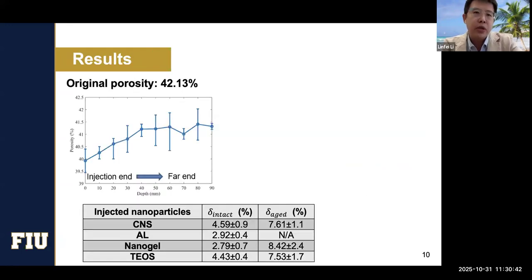So here are some of the results we have. First of all, we measured the porosity of the cement. As shown in the previous slides, the cement itself has around 40% porosity. We measured exactly the same, and got 42.13%. Then we set up the sample to run in the test, and after 12 hours, we took it out.